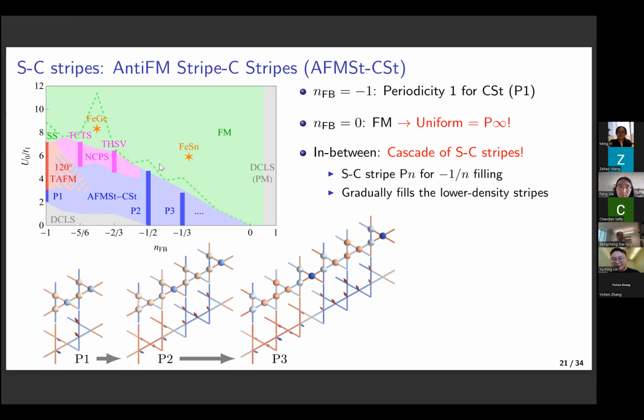So that's a very good point. If you're interested, you can check the appendix of our paper, where we show that if you go away from these commensurate fillings, you could still have this kind of periodic stripe orders, but they may not be as elegant as what I have shown here. For example, you may have one stripe of spin down and 3 stripes of spin up, forming a ferromagnetic order, something like that. The cases I showed here are all antiferromagnetic because they are at the simple -1/n filling. Yeah. So I guess it will be somehow attracted to the nearest P/Q with co-prime P and Q, something like that. Yeah, that's my impression. I see.